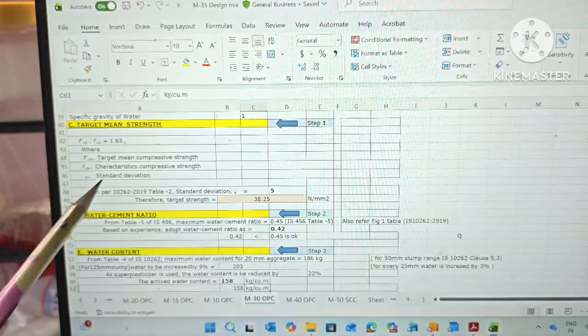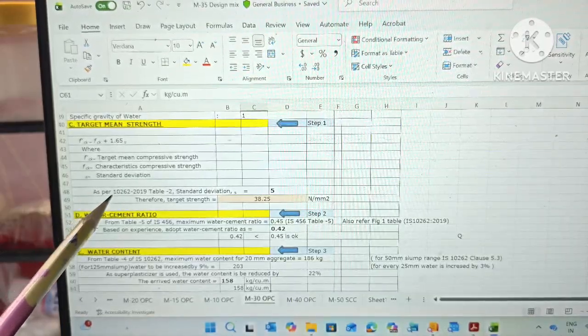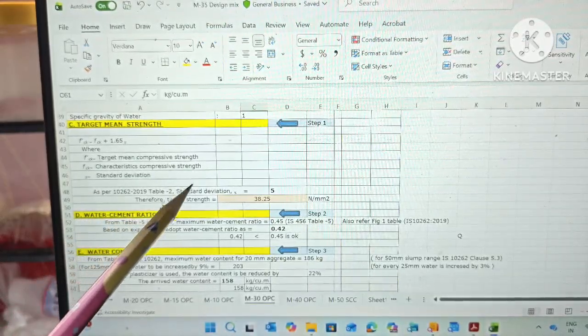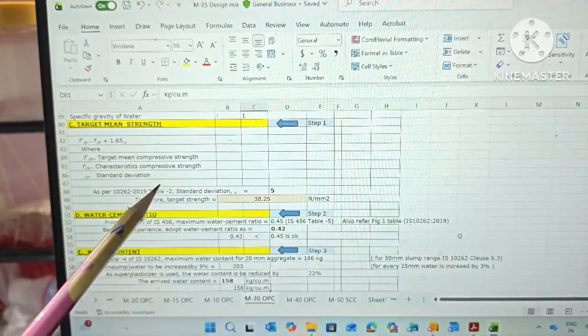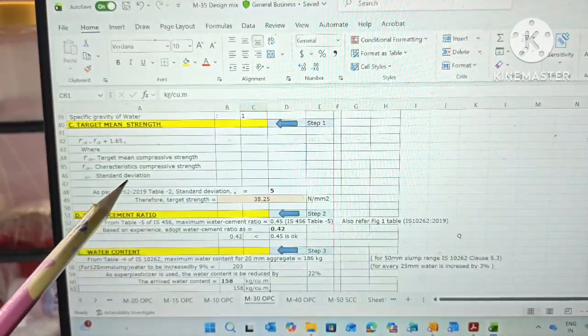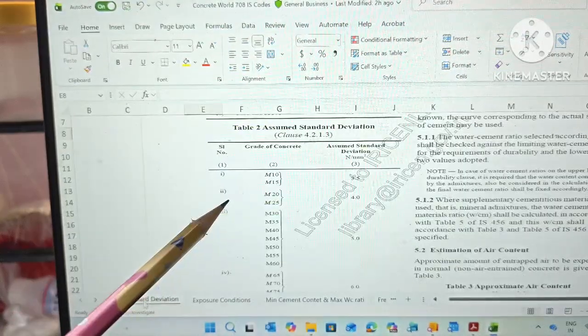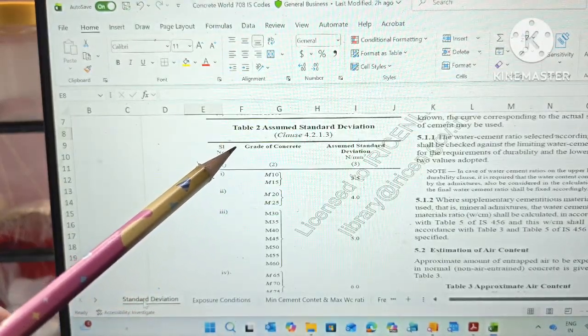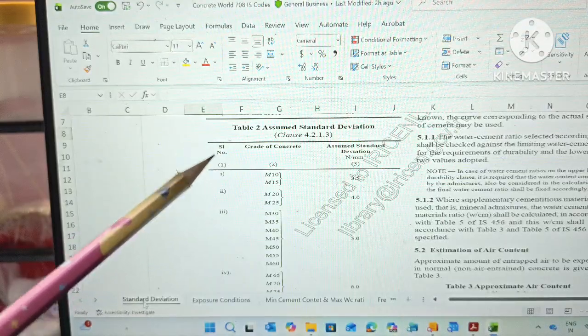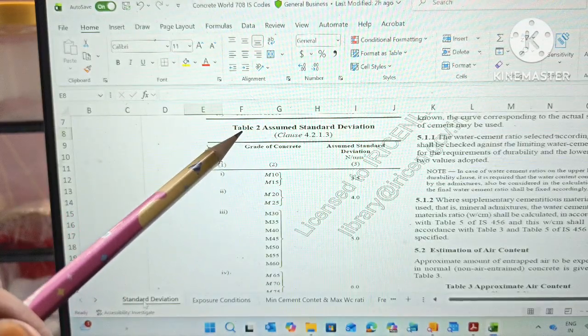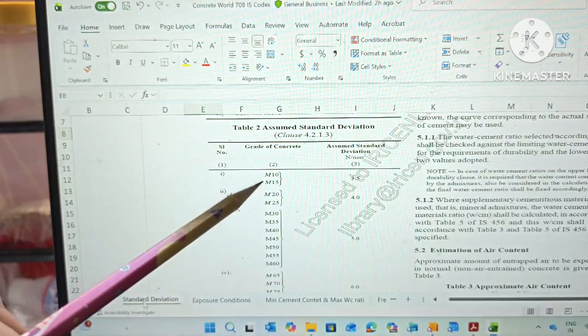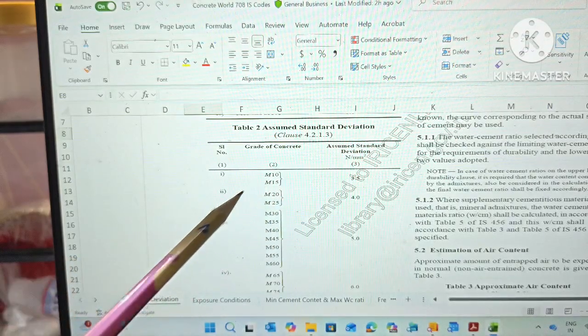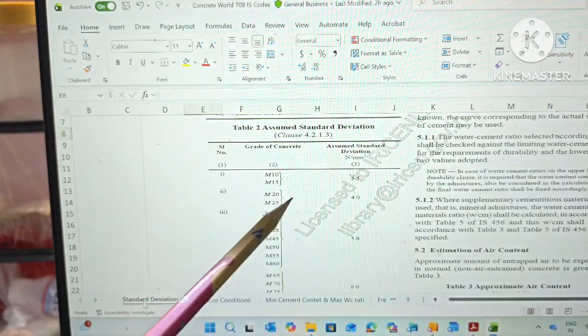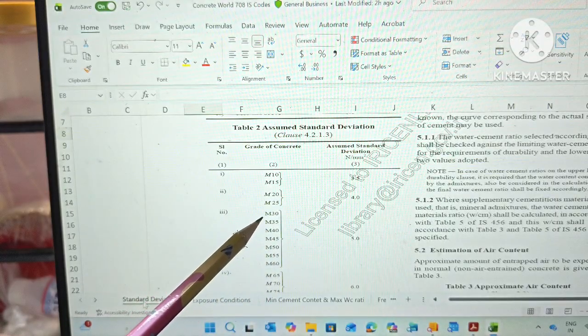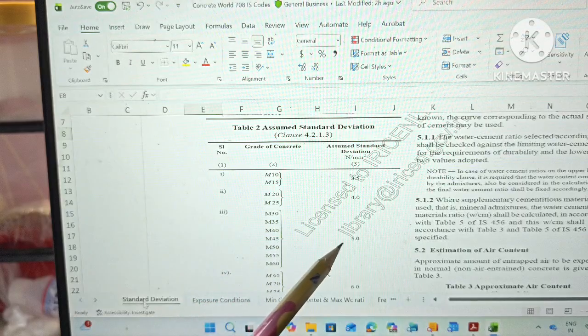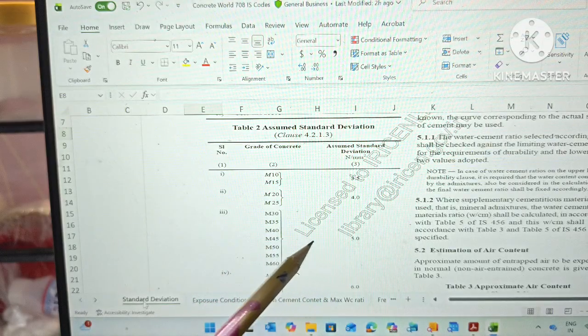Now, how do we determine the value of S? As per IS 10262-2019 table 2, standard deviation S is equal to 5. So let's go to the IS 10262-2019 table number 2. Friends, you can see table number 2. In table number 2, the assumed standard deviation for different grade of concrete is given. For M10 and M15, standard deviation is 3.5. For M20 and 25, standard deviation is 4. And for grade M30 to M60, standard deviation is 5. So here we will consider standard deviation as 5.